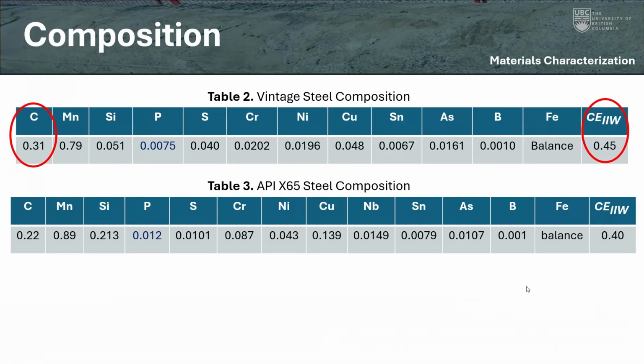I also want to comment on the high sulfur content. So in the vintage steel, it's 0.04 compared to 0.01. This also exceeds the typical maximum limit of 0.015 weight percent, which is seen in API 5L for X42 and X80 line pipe steels. So this can also imply a dirty steel prone to high density of manganese sulfide inclusion.